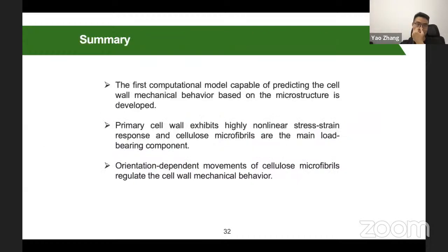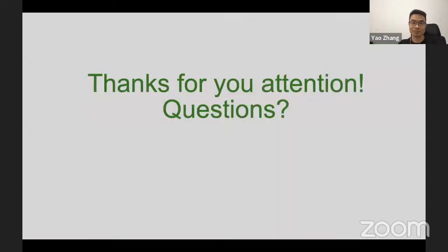So what we get is that we developed the first model which captures cell wall mechanical behavior based on the microstructure. And also we found that the primary cell wall has a highly nonlinear stress-strain response. The cellulose fibers are the main load-bearing component. And finally, we found that the orientation-dependent movement of the cellulose fibers regulates the cell wall mechanical behavior. Okay, that's my work.